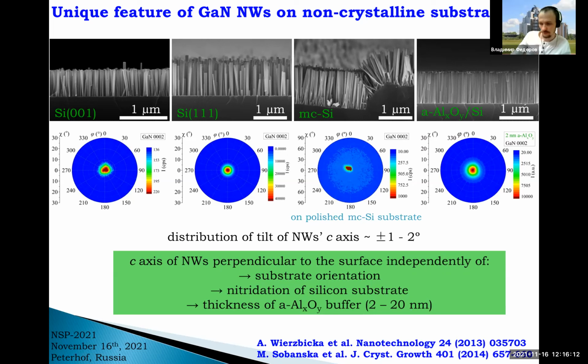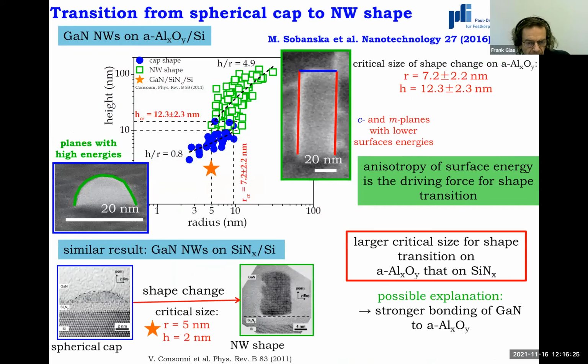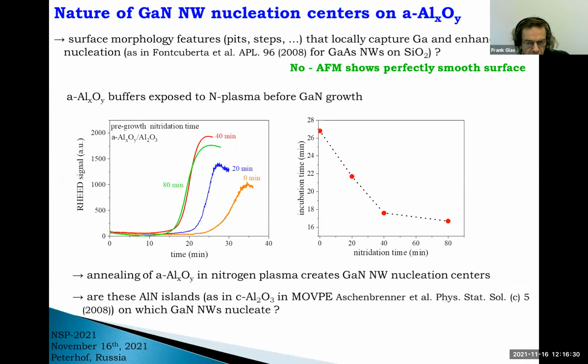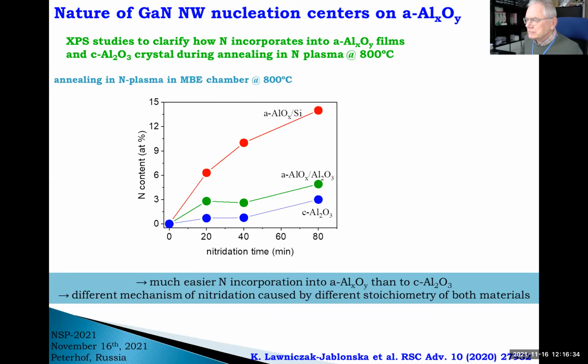Thank you. Frank? Thank you, Zbig, for this very comprehensive talk. I have a small question about your XPS results, the nitridation of the amorphous aluminum oxide. If I understood well, it seems to depend on the underlying substrate. Why is this? Thank you, Frank, for this question. I expected it actually. The model is that incorporation of nitrogen into aluminum oxide depends on the concentration of oxygen vacancies. In this case, you have plenty of oxygen vacancies available, while in this case, you have a supply of oxygen from sapphire. This is how we explain it. All right, thank you. A more precise model with creation of various phases is given right here in this paper. But this is a general answer.